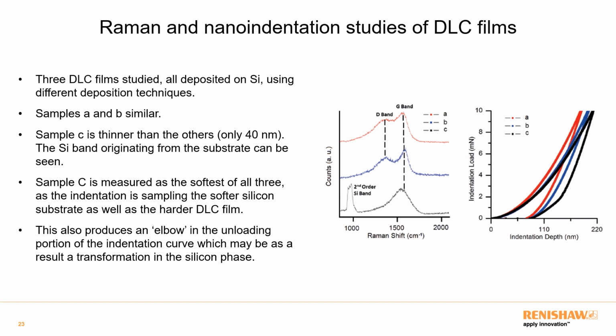If we now look at the load indentation depth figure on the right hand side, you can see how these 3 different films vary. Film A and film B have quite similar properties. To indent film A, we need to apply more force than film B, so it's clearly a harder film. With regards to film C, though, we can see quite a bit of difference. It's a lot softer, so we're getting much deeper indents with the same level of force. But also on the unloading curve, we see an elbow here. So it's not quite elastic in its recovery. Something is going on here. What we suspect is happening is you're getting a transformation in the silicon phase underneath the film. Because this film is so thin, it's not really protecting the silicon underneath. So we're measuring just as much of the silicon changes as we are of the film changes.